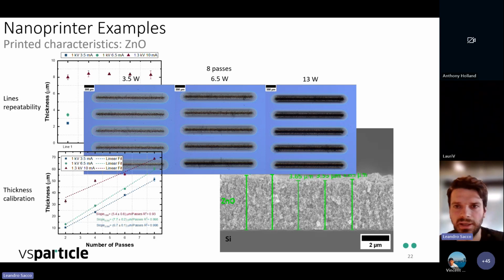What is important here, I can give some details about the procedure, because essentially we cut the silicon oxide substrate with a diamond, and then we did some cross-sections with a SEM, and we measured the thickness of these lines. So here are 2 things. You can see that the adhesion is very good, because the lines survive after we cut the wafer, as we observed in the cross-section SEM. And also we measured the thickness variation of these 5 lines, and we observe that the reproducibility is relatively high, because we have less than 3% variation between the thickness of each line.